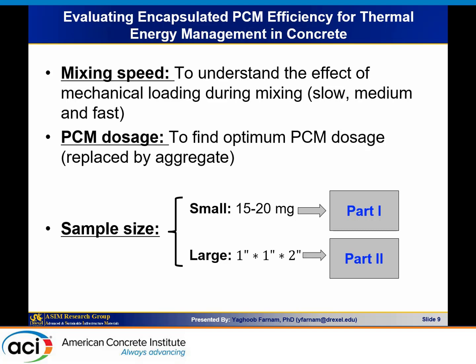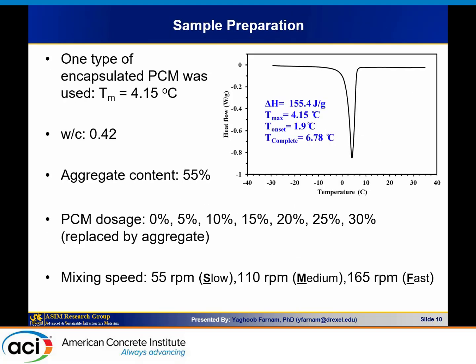And then the other question that we had was, what would be the effect of sample size on the thermal performance? Smaller samples are going to behave totally differently than larger samples. We're talking about thermal diffusion and thermal conductivity, which depend upon the distance of the heat transfer inside your system. So you have to be very careful. Larger samples are going to behave differently than smaller samples, and we wanted to see what the main difference is if we scale up the sample size.